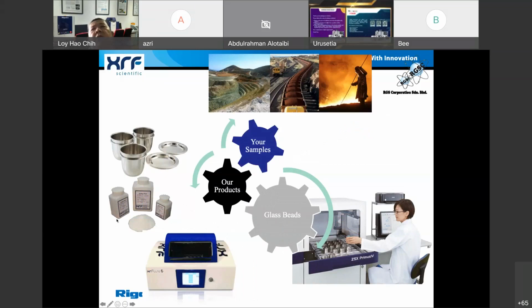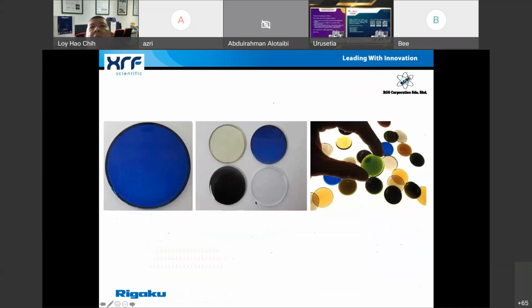In the fusion process, we need machines. In this picture, this is a fully automated fusion machine. Besides that, we need two very important ingredients, which are the lithium borate flux and also platinum crucibles or platinum ware. So in all lithium borate fusion, we need platinum ware. This is very important.